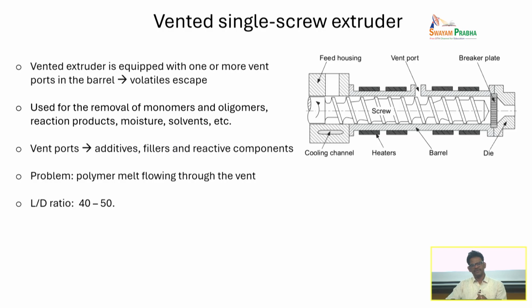So now we can go a little advanced design of this extruder. What we saw is a very primitive design, but typically what happens is that when you extrude, you are increasing temperature, and the polymer that you have may not be of completely single component polymer. It may have certain other additives that may become volatile, and they may want to evaporate. Okay, and if you don't remove that vapor, that bubble can get integrated into the product that you make.